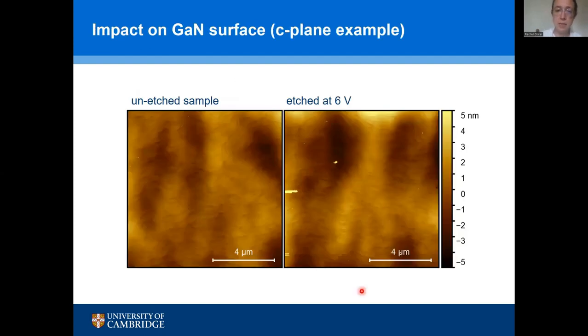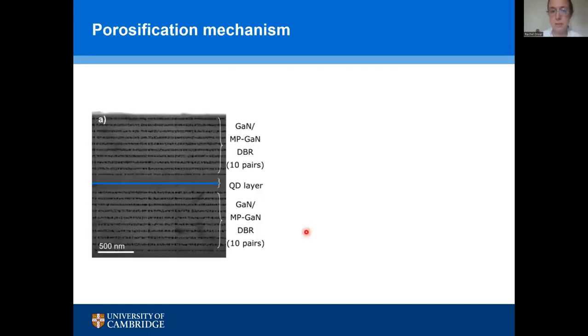And I said that the etching happens through the top surface. The thing that's rather remarkable is you might think that would completely damage and destroy the top surface. But what I've got here are atomic force microscopy images. They are atomically resolved in the Z direction. So these bands you can see are actually single and double atomic height steps in the gallium nitride. But before and after etching, we haven't really damaged the surface at all. There's a few bits of contamination after etching. We're better at cleaning the samples now, so that's less of an issue. But apart from that, there's nothing to see in terms of changes at the surface.